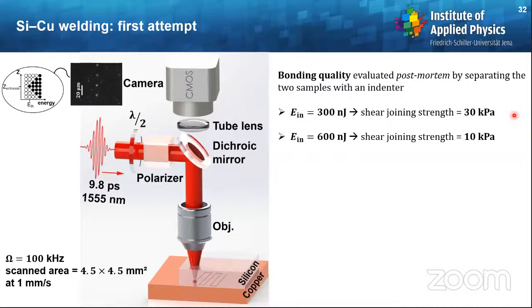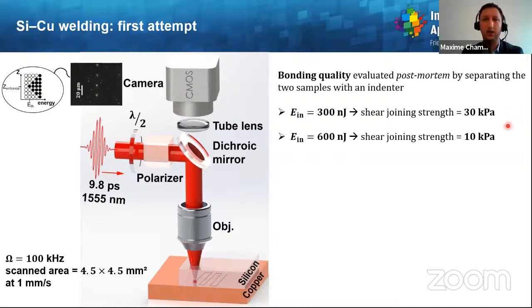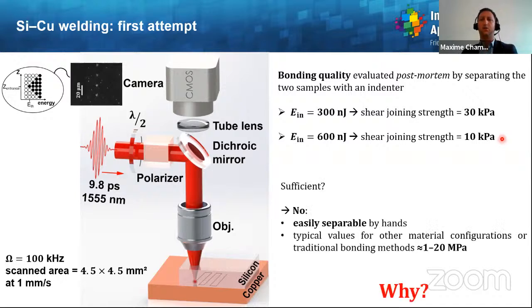Okay. Then what happens if we double the input pulse energy and go to 600 nanojoules? Then the shear joining strength is 3 times lower, 10 kilopascal. Okay, so this is weird, but the main question is, is that sufficient? And sadly, the answer is no. Actually, in this case, the two materials are easily separable by hands, while typical values obtained for other material configurations or traditional bonding methods are on the order of 1 to 20 megapascal. So now we have to explain why.